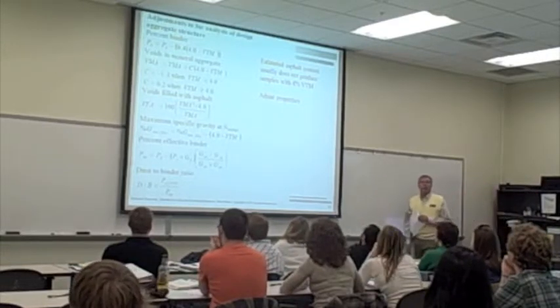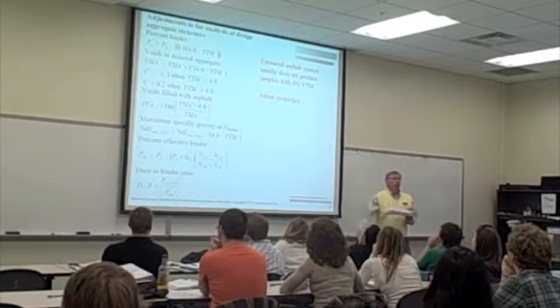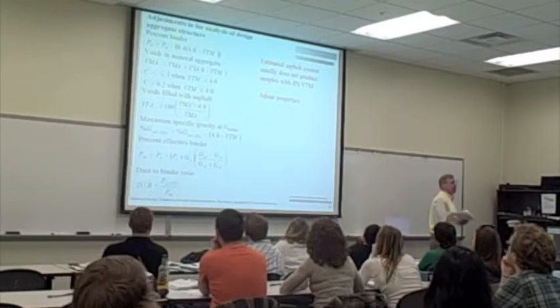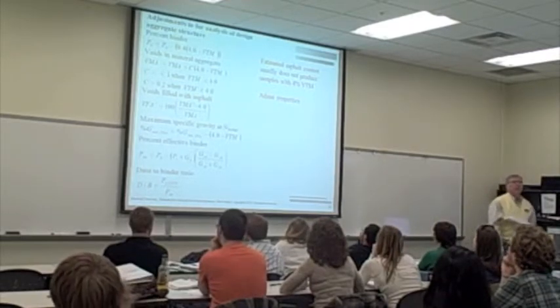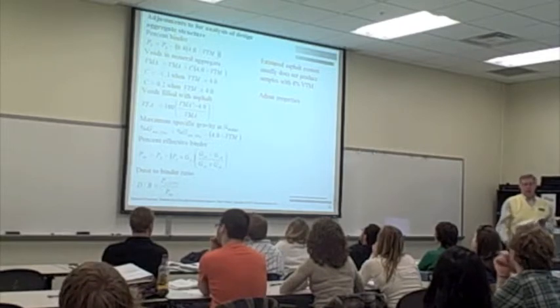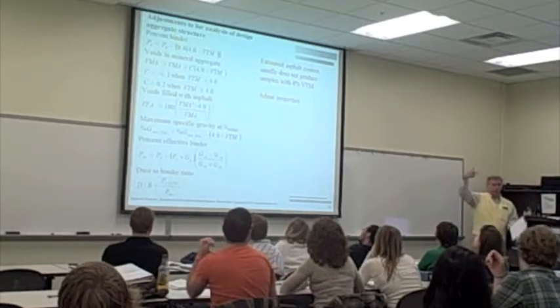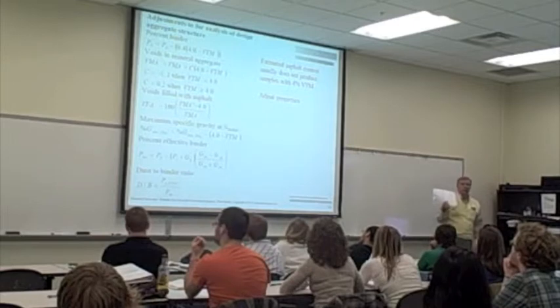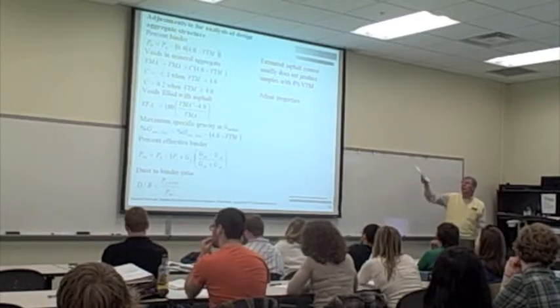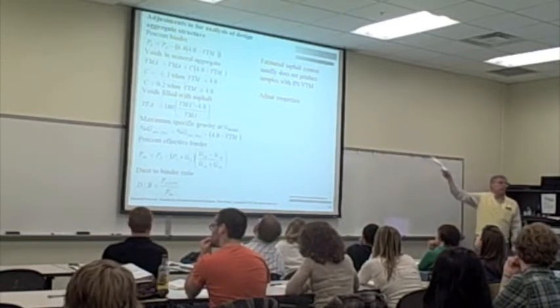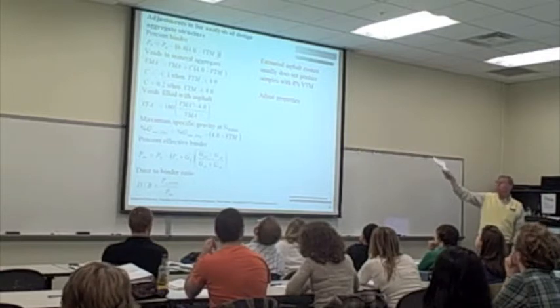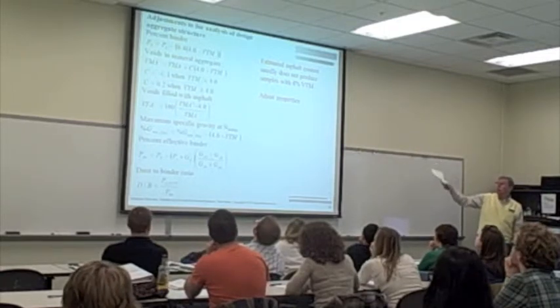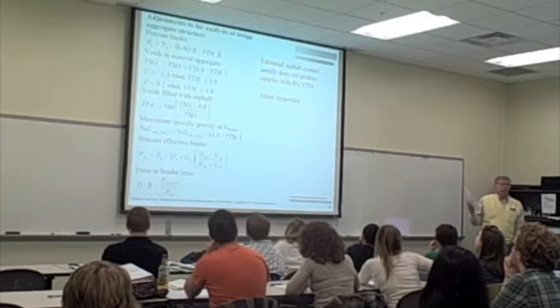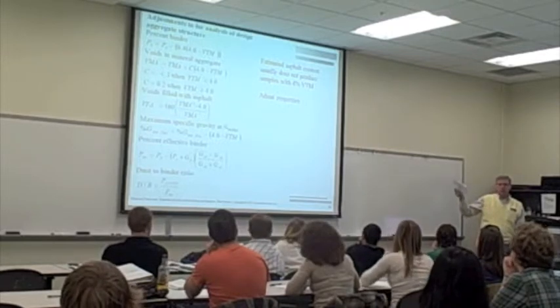Now we wanted 4% air voids. We go through the volumetric analysis and we find out that our samples didn't actually give us 4% air voids. So we do a mathematical adjustment, and that's on the top right column. And we go through and we get an adjusted percent binder. How much binder would I need to get approximately 4% air voids? We get an adjusted VMA, VFA. By the way, pavement engineers love to talk in initials.